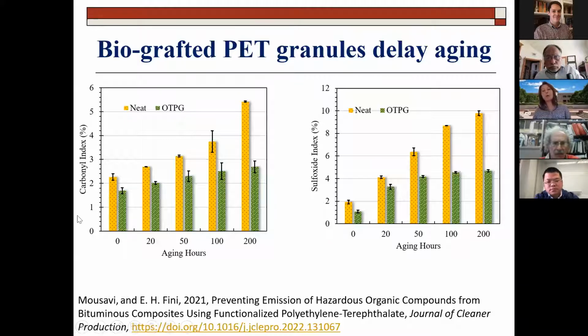But overall, what you see on the top is aging. I just showed you the aging change over time. Look at the x-axis, it is 200 hours. If it's neat Arizona asphalt, it's the yellow. Look at how the aging changes. Carbonyl index is an indicator of oxidation. Sulfoxide index is another one, with oxygen bonds to asphalt. So as the aging progresses, that's what we expect. Oxygen bonds and the yellow bars keep going up and up and up. If I continue beyond 200 hours, it still keeps going up.